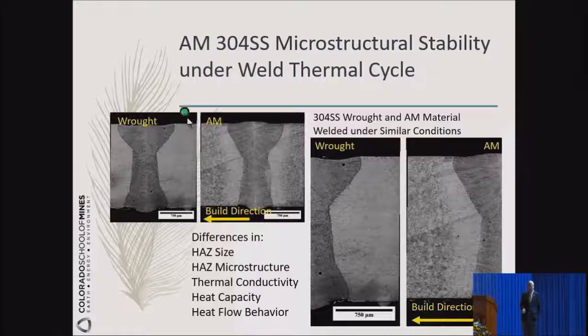For example, when you weld on a wrought piece of material, 304 stainless steel, and you weld on a 304 AM'd material, you notice just the metallography preparation will tell you that something has happened here that is different. The heat affected zone size is different. The heat affected zone microstructure is different. So is it possible that the thermal conductivity has changed, the heat capacity has changed, heat flow behavior has changed? All those questions remain to be answered, and a lot of the thermal analysis work can be done here.